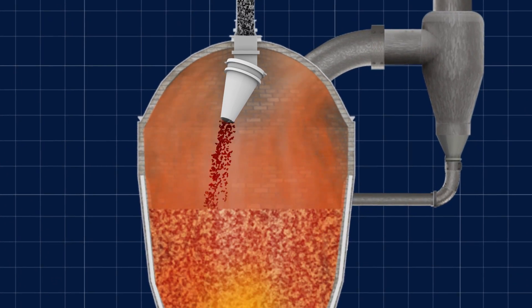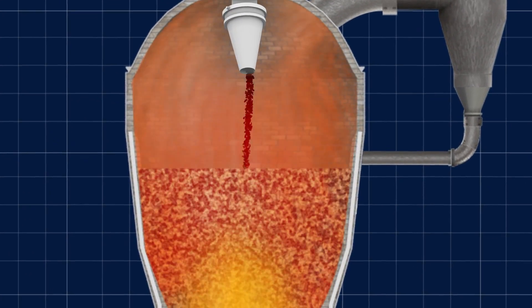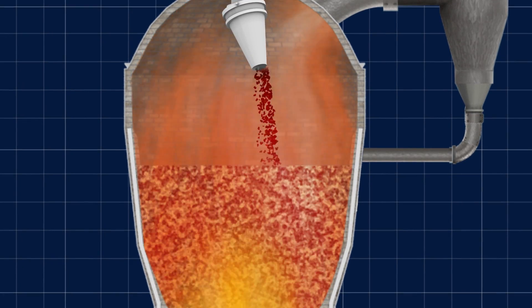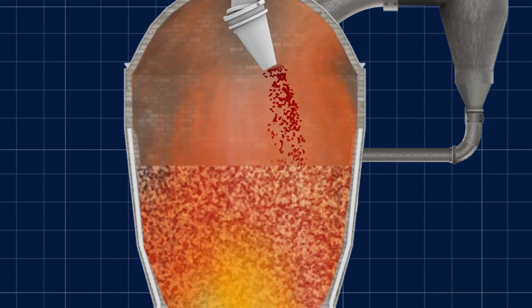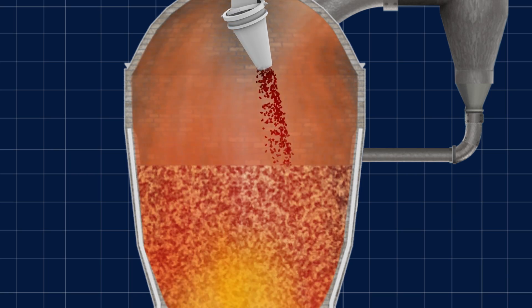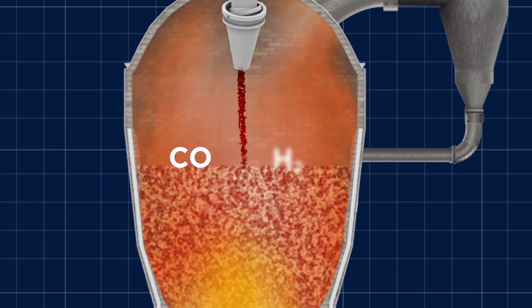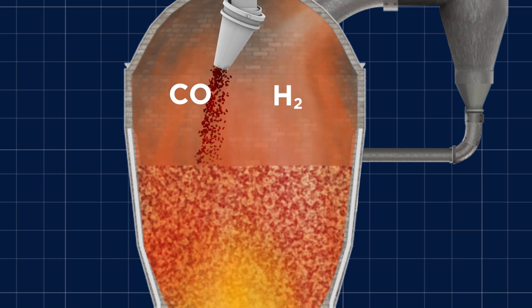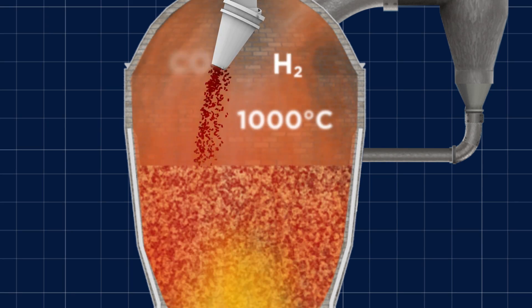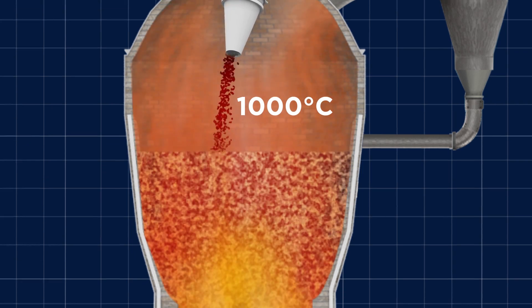The gimbal-top allows an exact distribution of the burden within the melter gasifier to be achieved. After the coal drops onto the top of the charge bed, degassing takes place. The released hydrocarbons are immediately dissociated to carbon monoxide and hydrogen, due to the high prevailing temperatures that exceed 1,000 degrees Celsius in the dome of the melter gasifier.